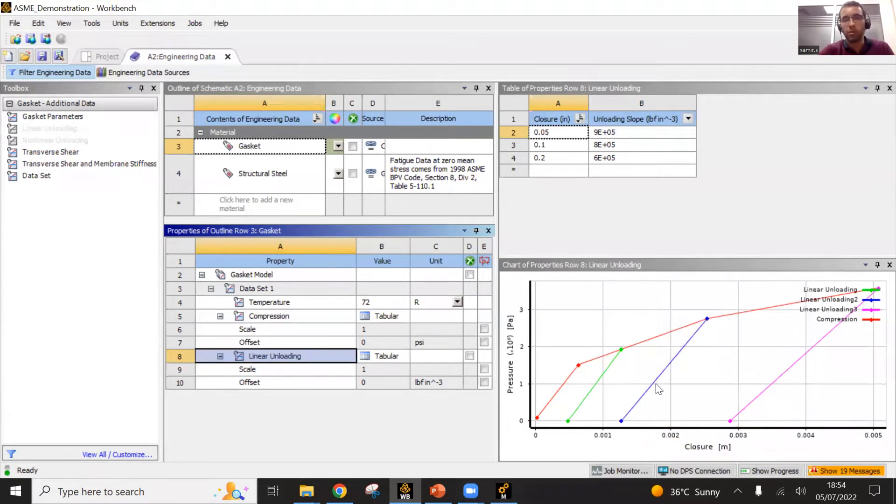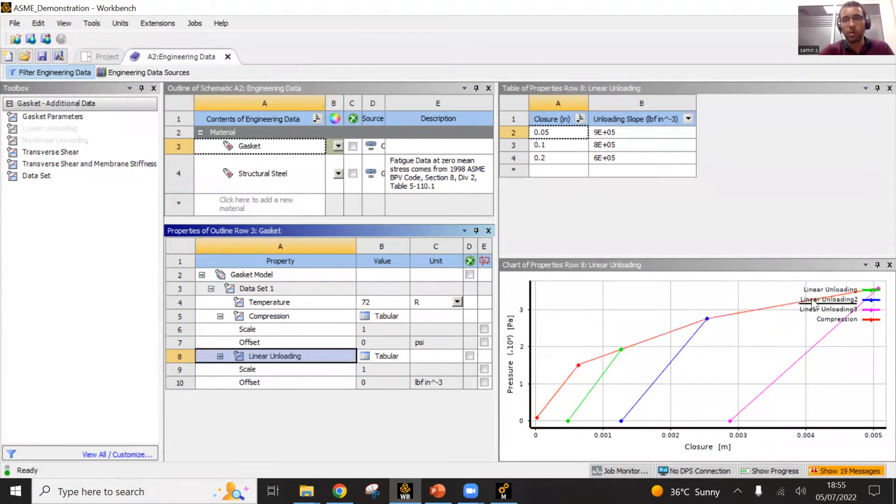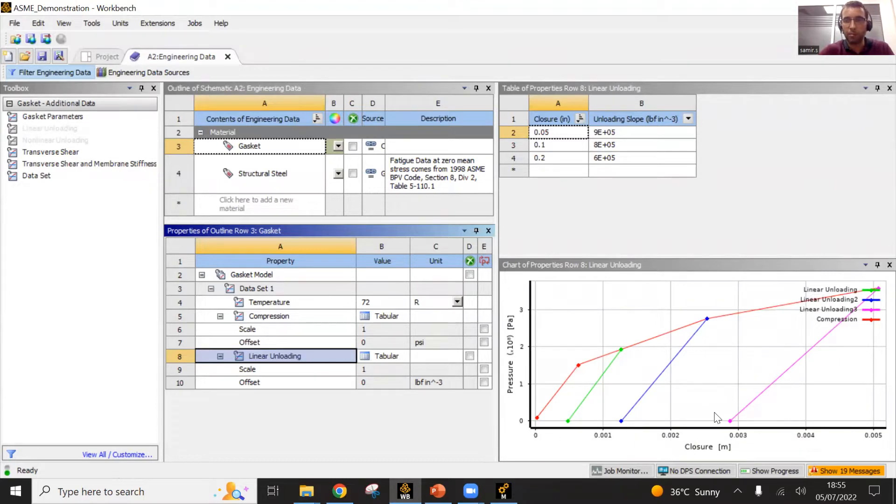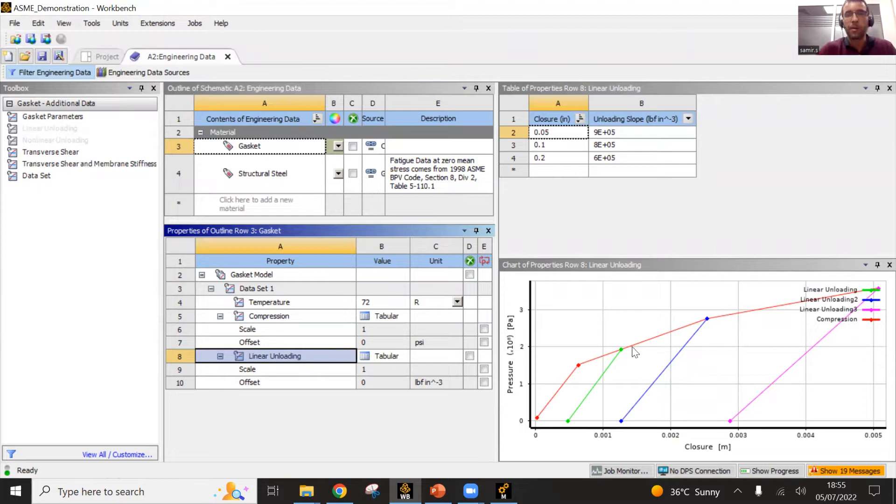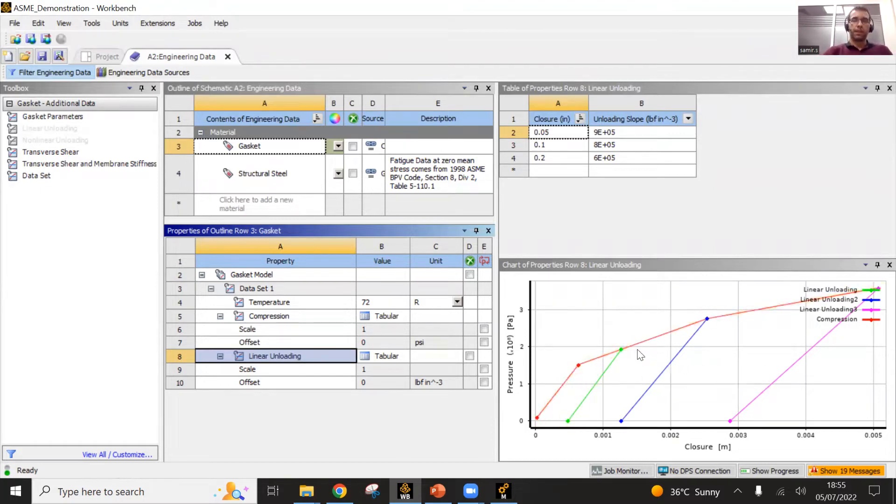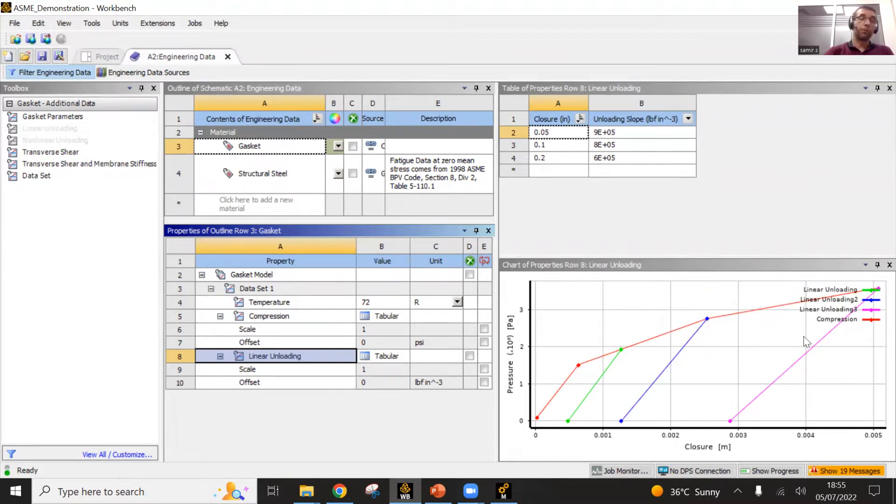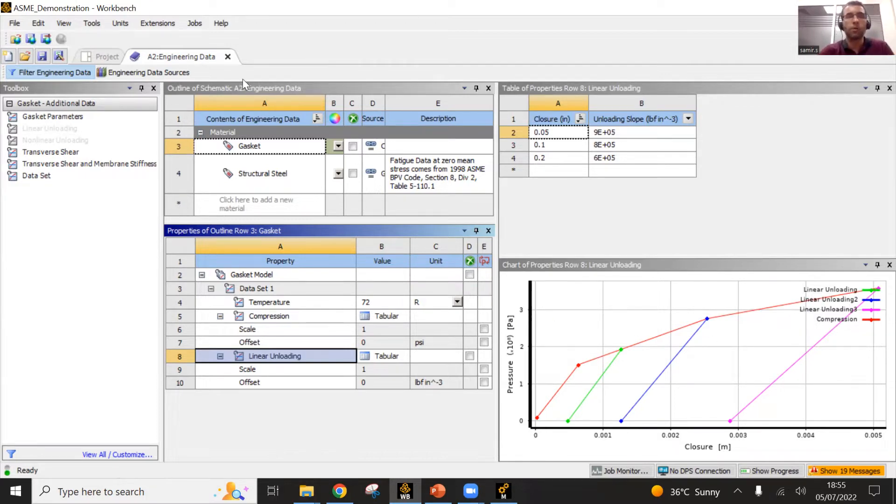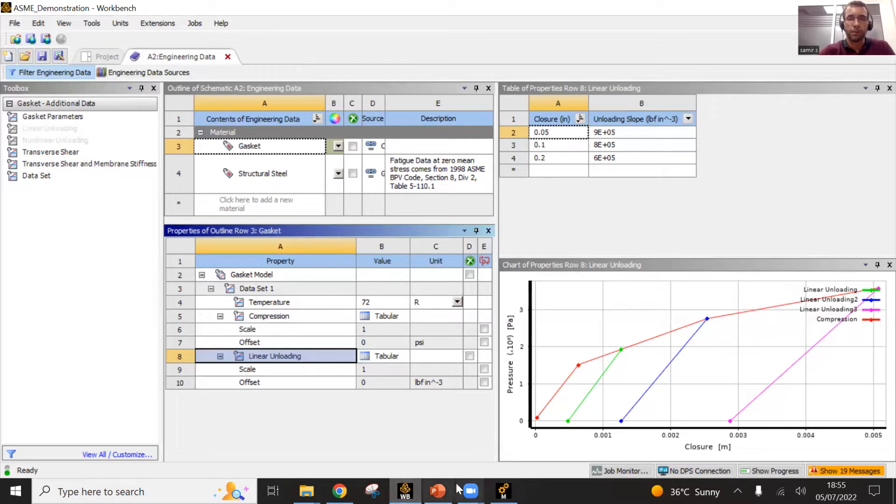If you reload your gasket from this point, you will follow this curve again, loading and coming back to the main curve and continue. If you unload it here, you will come back through this way. So you will have all this permanent deformation which is there. This is the concept of the gaskets. And this is called the linear unloading curve, which the gasket provider should give you. But you can apply it in ANSYS and that is what is complexifying the analysis.